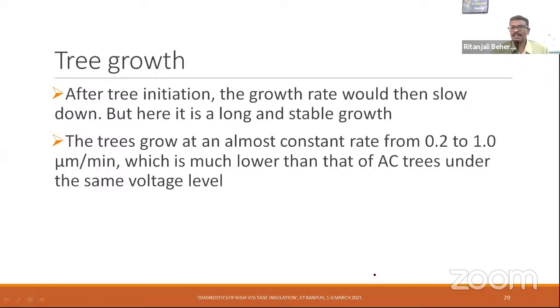Which is much lower than that of AC trees under the same voltage level. In fact, if we compare the tree progress, in one report it says 50 kV. Here in this case, the applied voltage was about 50 kV, whereas this situation is more or less similar to the AC voltage at 15 kV. So 50 kV and 15 kV. That is the level of comparison. That is the level of stress with which we compare and then try to understand the treeing progression.